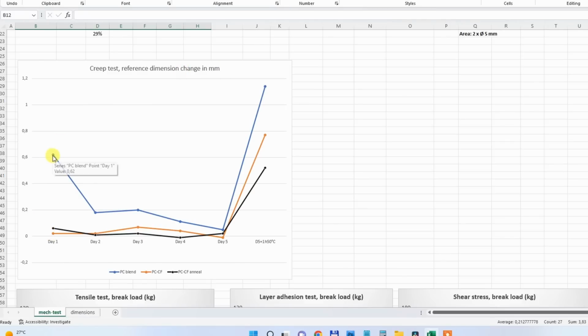After 1 day, I can see some creeping on the regular PC blend, but almost no creeping on the carbon fiber versions. But this is also a very low value. After this, basically the creeping stopped. These are such small values that it could even be an error in the measuring. And after placing 1 hour on 50 degrees Celsius, I can see some additional creeping, but in this order. So the biggest was with the PC blend, then carbon fiber version, and this is annealed version with the smallest creeping on this higher temperature.